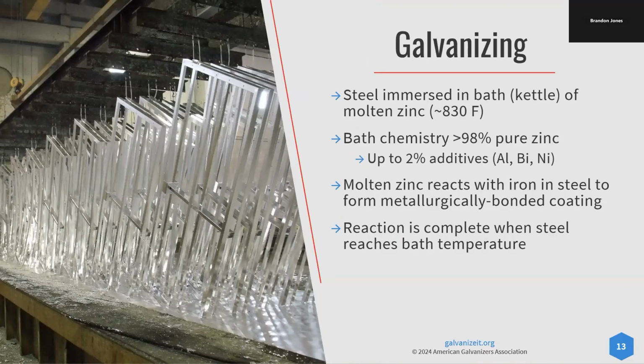And then comes the actual galvanizing process. Steel is fully immersed in a bath of molten hot zinc, about 830 to 850 degrees Fahrenheit. Bath chemistry per ASTM specifications has to be at least 98% pure zinc. Most every galvanizer I know is running more like 99.5, 99.6% pure zinc. Up to 2% additives include aluminum, bismuth, and nickel, which have no effect on the coating whatsoever, mostly just the fluidity of the bath. Molten zinc reacts metallurgically to form a bonded coating, and the reaction is complete when the steel reaches the bath temperature. Depending on how big the piece is, it could be as short as 2 minutes all the way up to about 15.